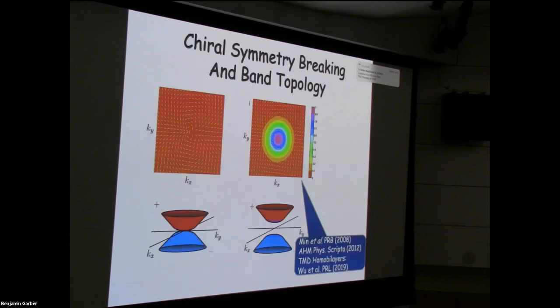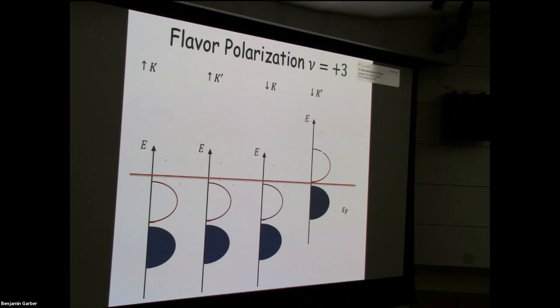so this measurement partly reflects topology of these valley projected bands. They usually have non-zero Chern numbers that they basically inherit from the Dirac electron starting point, the Dirac electron model of the two layers that combine together. I don't have time to explain this slide, but even graphene and even AB Bernal bilayer graphene without a moiré pattern, their valley projected bands tend to have non-zero Chern numbers as well. And there are perhaps some experimental manifestations of that, but because of forming these moiré bands, you can get much stronger manifestations